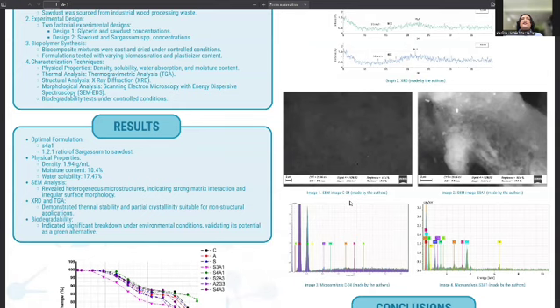Structural and thermal analysis: the SEM revealed a heterogeneous, irregular surface, suggesting a strong bonding between the biopolymer matrix and fillers. XRD indicated partial crystallinity, while TGA confirmed good thermal stability, suitable for non-structural uses where moderate heat resistance is needed.